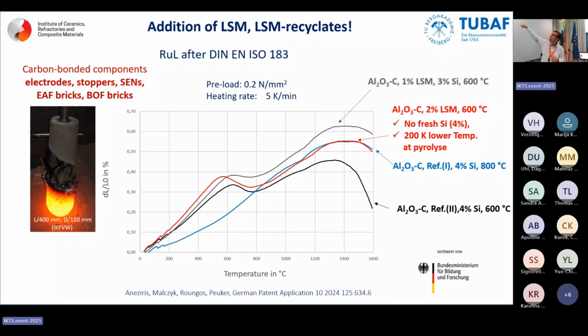Pyrolyzed at 800 degrees, pyrolyzed at 600 degrees. And we see if we add the lanthanum strontium manganate, we can avoid silicon metal, and we can also go 200 Kelvin lower with the temperature. So reactions that help us.